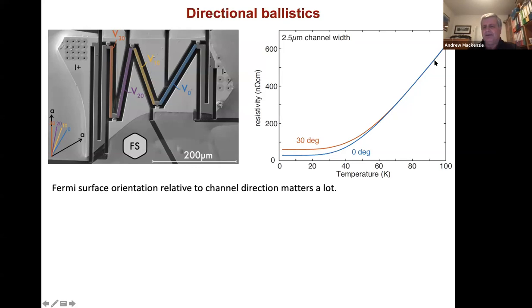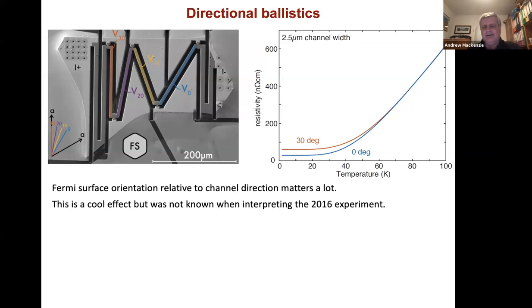However, when we go down to low temperatures and the phonon scattering dies out and we go into a non-local transport regime, what we discover is a ballistic effect, which makes transport along one of these two directions over twice as easy as the other. That's the easy direction, and that's the hard direction. And the trouble is that when we interpreted the 2016 experiment without taking into account these orientation effects, we certainly built in a systematic issue with the analysis. What that means is that the 2016 experiment needs to be carefully repeated and re-examined, taking into account these directional effects. And that's something that we're doing now in the group.